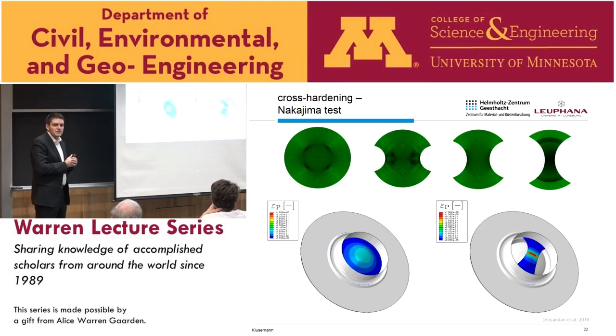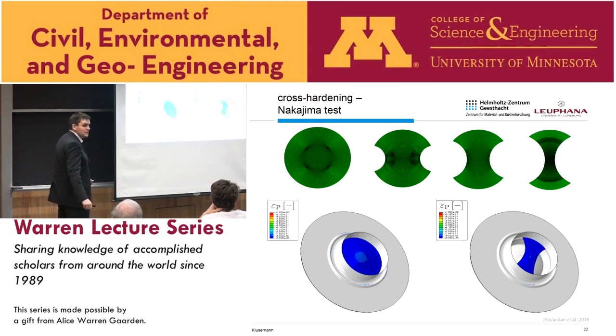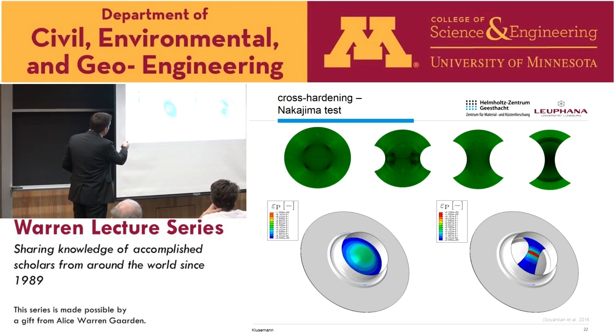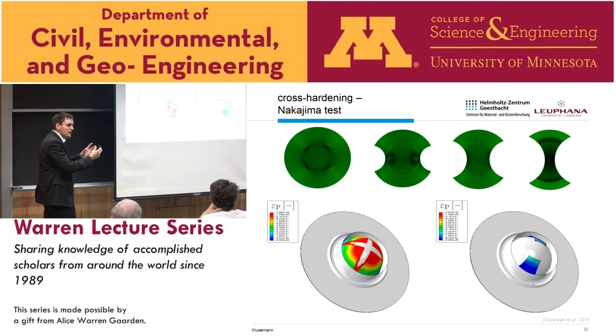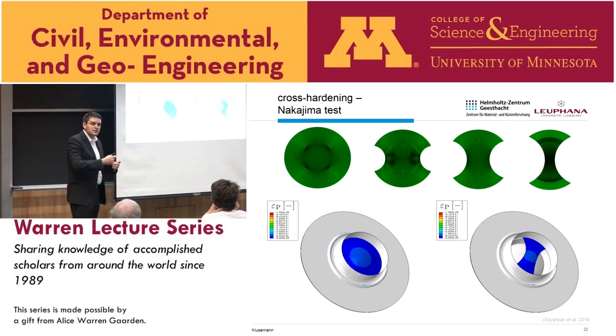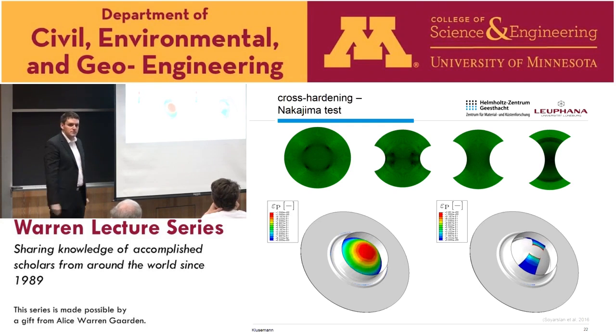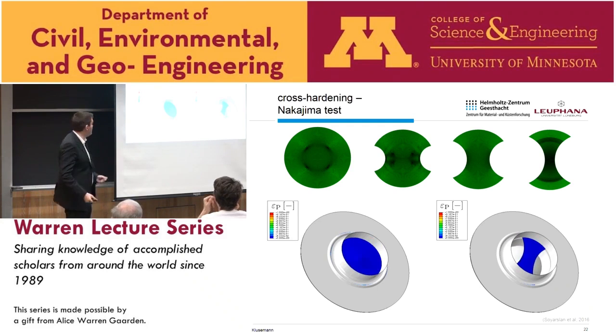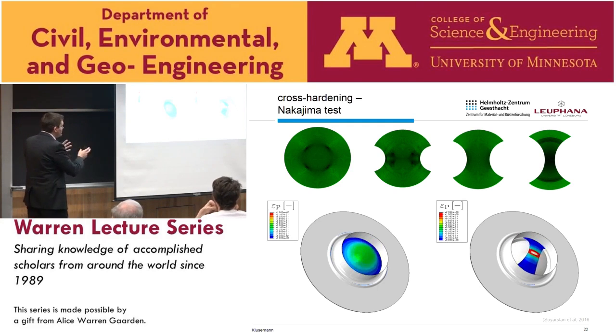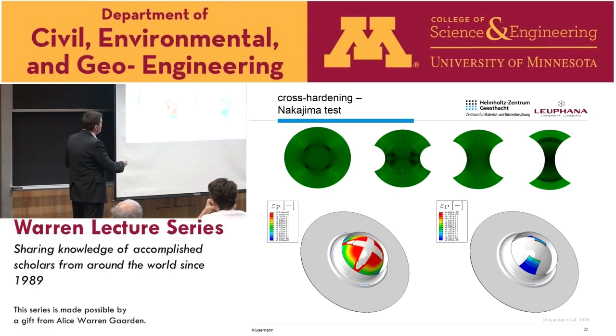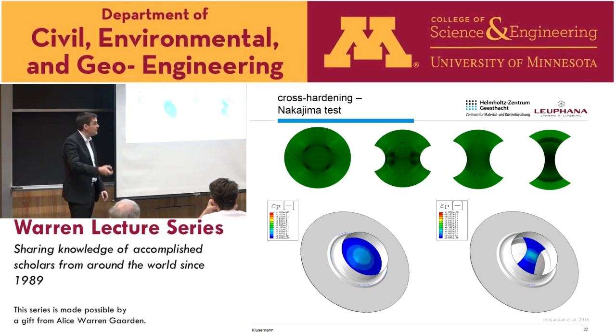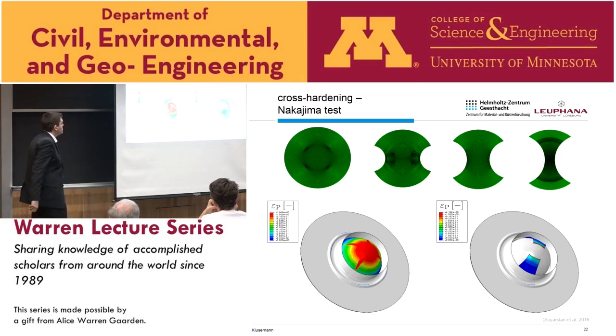Okay, so we went a step further and wanted to see what might be the effect of this cross-hardening contribution with respect to, for example, its forming limit capabilities. And for that, we performed some Nakajima tests. For a Nakajima test, you can, in principle, prepare the specimen in this way. So you cut out certain radii, and by that you can generate different stress states inside of your material. You have a very nice choice to actually investigate these different strain states.